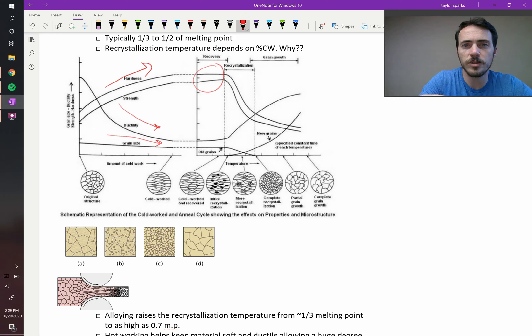Initially, at this low temperature regime, not a lot's happening. You're getting what's called recovery. Basically, all you're going to be able to do there is clean up the microstructure. If it was filled with defects, maybe you can start to get rid of some of those defects. But if you reach a certain temperature right here, shown with this dotted line, that's when you get recrystallization. Now, entirely new grains are growing. You can see, here they are, like these little tiny grains. They started to grow there, and now they're getting larger and larger until you get complete recrystallization there.